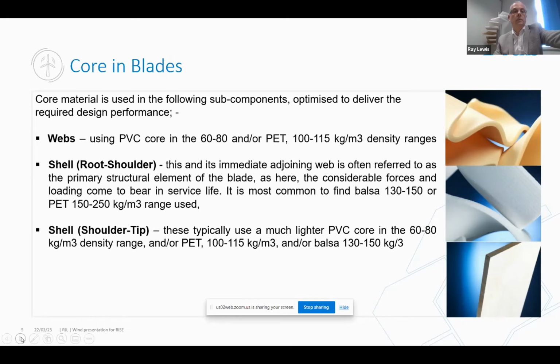In the shell, you have the root to shoulder area, which is really the thickest section of the blade. And there's a lot of forces that come into being here. Balsa has been a default for many people to use because of the high compression modulus properties of balsa. PVC was really quite expensive, so to use anything comparable, it would be such a significant cost, although some people did use that. You could engineer out that disadvantage, and some suppliers did, but in the case of infusion designs,